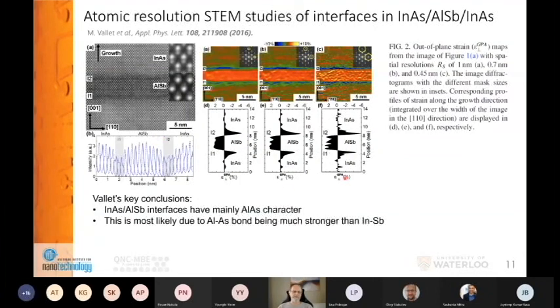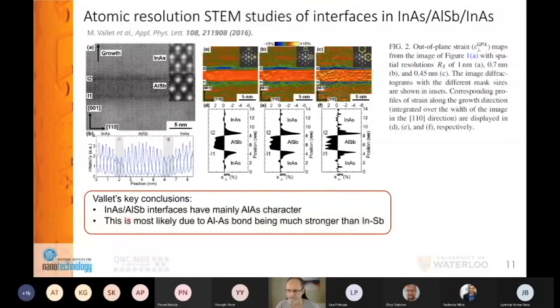Fairly recent work has been done by a group in France looking at those interfaces in the context of quantum cascade lasers. This is high resolution scanning transmission electron microscopy, where they were mapping the strains around the interfaces and also trying to map the atoms themselves. The main conclusion they arrived at was that the indium arsenide, aluminium antimonide interface has mainly aluminium arsenide character unless some special precautions are taken. They attributed it to the aluminium arsenide bonds being much stronger than indium antimonide.